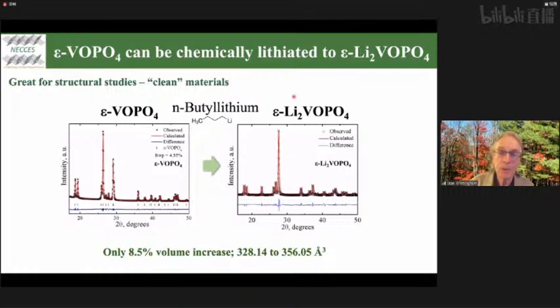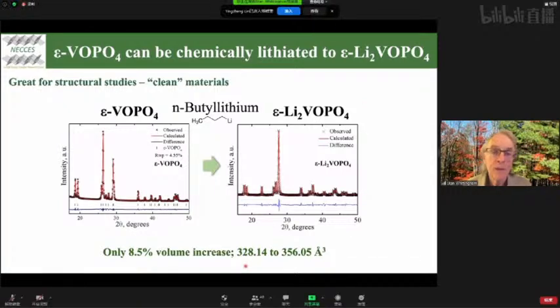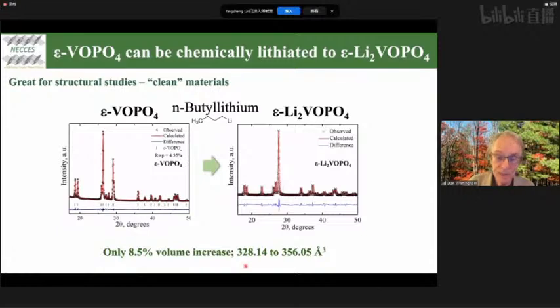And doing that, we were able to work out the structure of this material and of some of the other ordered materials. But probably most important is we found out when we put lithium into this material, the lattice only expanded by 8.5%. That's in fact less than what graphite expands, which gave us a clue that we could have a stable structure here that might allow us to put lithium in and out many, many times.